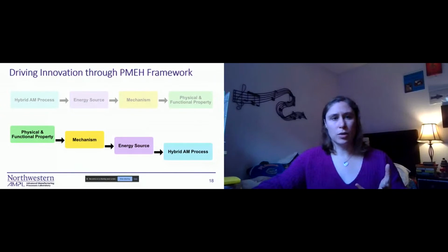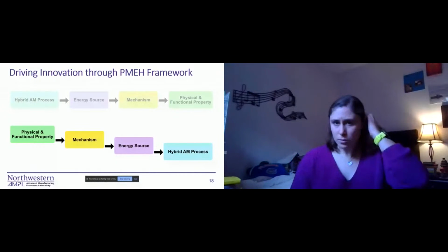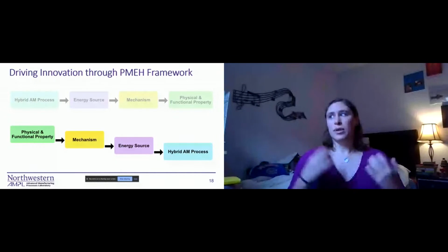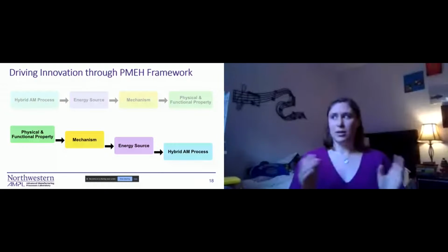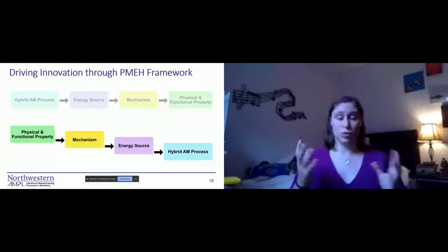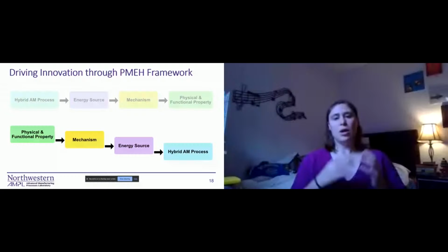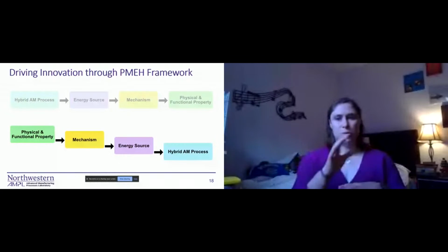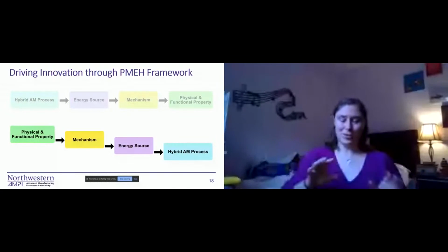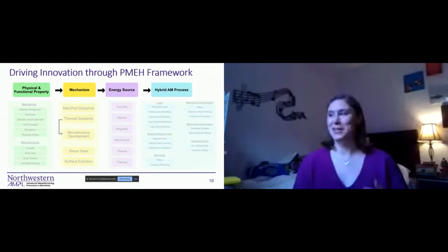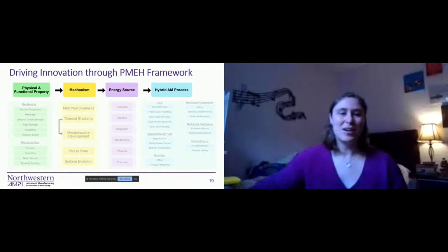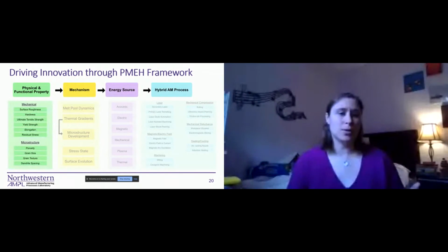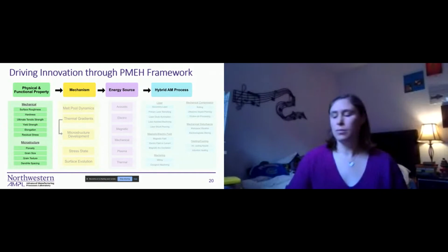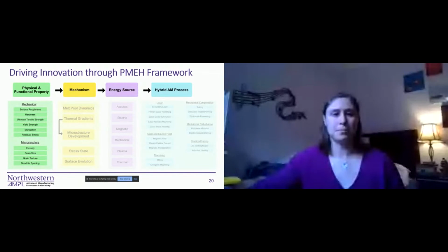So looking at this framework a little bit more in depth, I've categorized the current research within each step into major identifiable groups. I also connected major relationships between each of these blocks, which you can find in the paper itself. There are too many relationships to go over at this time, but looking at the major blocks in physical and functional properties, we have mechanical properties, the microstructure, and also the surface finish of the material.